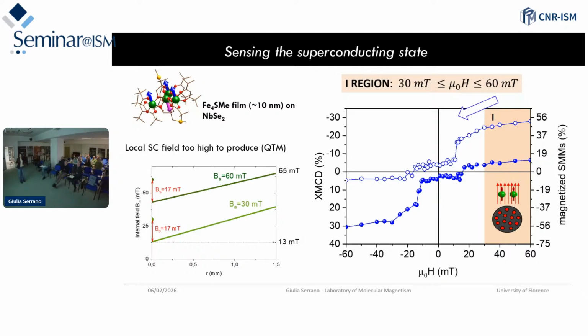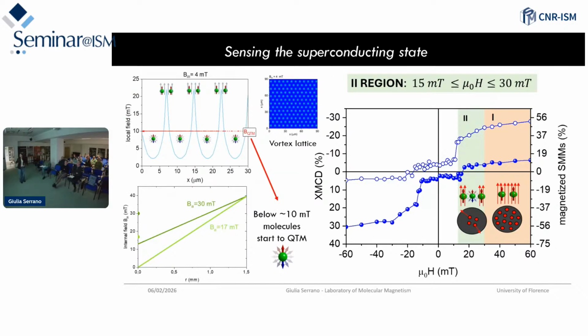Then, when we approach 30 millitesla, at this point the curve starts to deviate and to go down. So we are then exploring a second region of this hysteresis loop, in which the mean field of the vortex lattice is lowering as much as we lower the external field, but also, these are calculations done on the average field fluctuation of the superconductor.